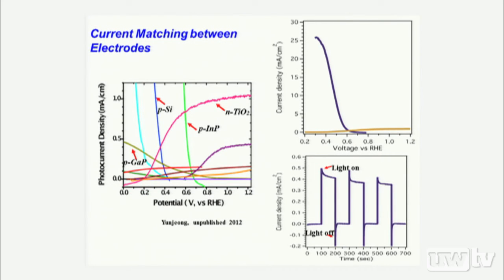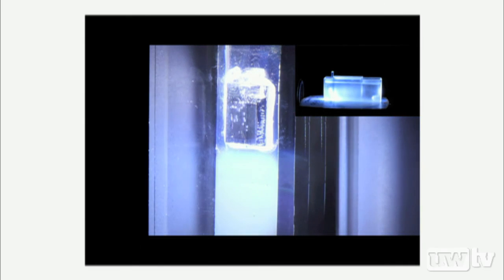By plotting the photo response of the photocathode and the photoanode, in the upper right corner, the blue curve is the photocathode, the silicon, and the yellowish curve is for TiO2. By simply combining the silicon and TiO2 nanowire arrays at zero bias, we can get a current density of around 0.4 milliamp per square centimeter under one sun irradiation. That corresponds to a solar to hydrogen energy conversion efficiency of roughly 0.5 to 0.6%. So we can do spontaneous water splitting now by simply combining a silicon nanowire array and a TiO2 nanowire array, with efficiency up to 0.5 to 0.6%.